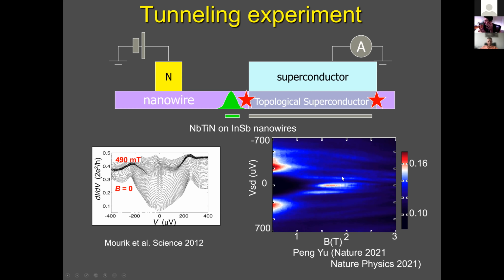Now, to give you a sense for energy scales here, what these millivolts mean. So this is 700 microvolts. The g factor of electrons in this material, this nanowire, is indium antimonide, is very large. It's 50. For free electron, it's 2. So we have a lot of Zeeman energy per magnetic field. So for 1 Tesla of magnetic field, from 1 to 2, for instance, it is equivalent to Zeeman splitting of 1.5 milli electron volts. And 1.5 milli electron volts is this entire range here. So if we had a state that had spin, it would move across this entire graph in just this one interval from 1 to 2 Tesla. Right? So the zero bias peak stays, from this point of view, impressively pinned to zero bias. And that is the reason we investigate it as Majorana.